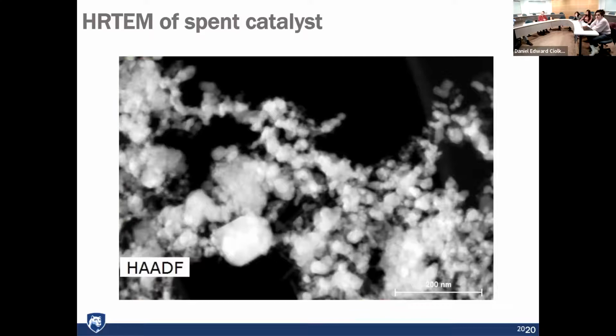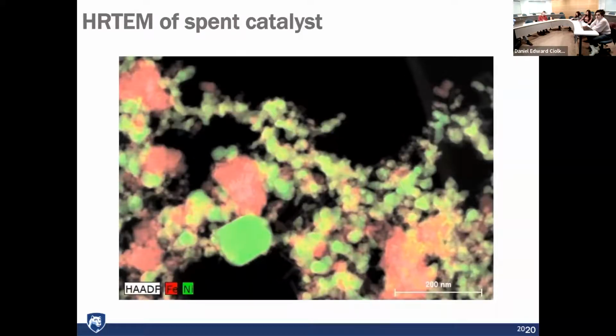And in this case, whereas before we saw an even mixture of all of the elements in our catalyst before the reaction, after the reaction, the elements have segregated. So now red is iron and green is nickel. They're no longer on top of one another. They're no longer mixed together. They're segregated. So our catalyst identity has changed, which means it wouldn't be something useful for us to reuse in another process.